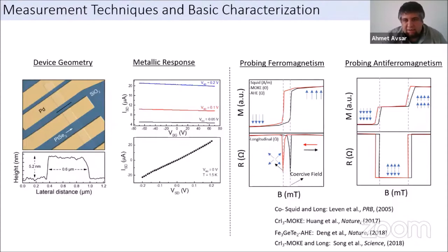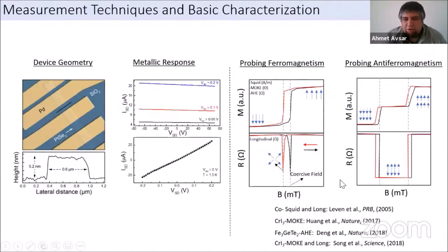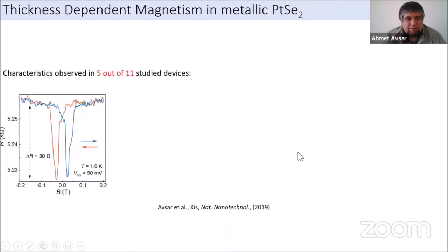So here I just added a short slide for some of the audience who are more familiar with SQUID or MOKE measurements, and this is the typical response you get with ferromagnetic samples, or with anomalous Hall effect measurements. But if you measure Rxx in longitudinal, this would be the response that you get for ferromagnetic samples. And if the material is antiferromagnetic, this is how the response would look on MOKE, okay? So you don't have any magnetic ordering near zero, and then once you go above some coercive field, the material becomes completely spin polarized. And if you would measure the resistance of this device, you would get a two-plateau system, right? And that's what we will be looking for in our devices.